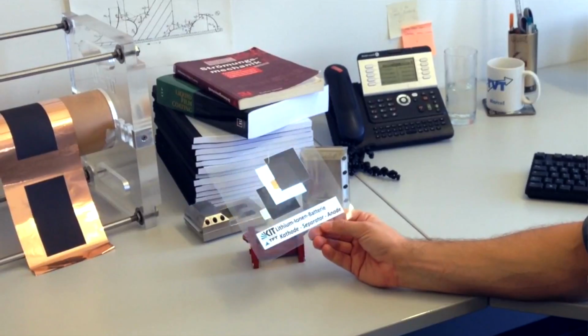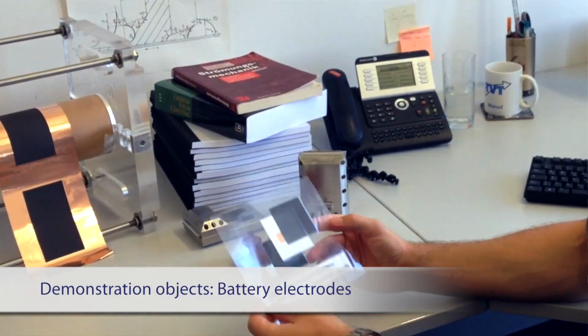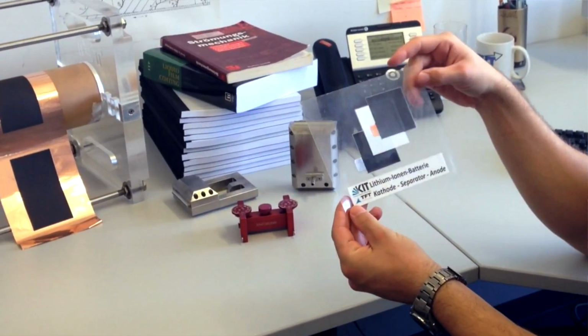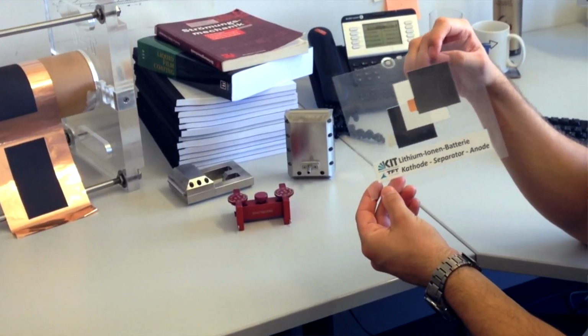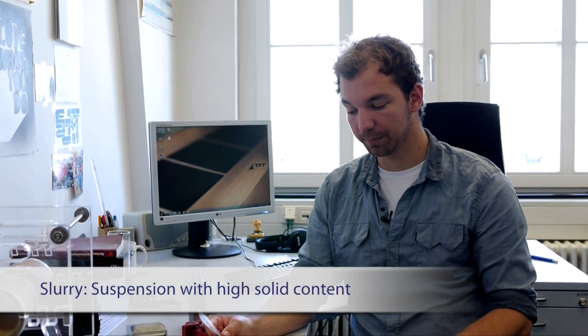Lithium-ion batteries are made of several really thin layers, and like every other battery we have a cathode, separator and anode. They are built up porous, so an ion-conducting electrolyte defines a continuous phase through the whole system. So these very thin layers of the electrodes have to be processed from a wet film, and therefore you have to mix your ingredients into a stable slurry. This slurry has to be coated as a thin film, like you see here, onto a metal foil. And then these films have to be dried, calendered, cut out as single electrode sheets, and then stacked to a cell together, packed, filled with electrolyte, and then formatted in a few cycles.